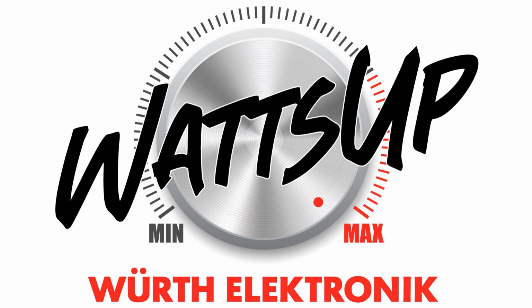So focusing on the graph shown on this slide, this core material could be used well for an inductor if the frequency of operation is between 1 and 3 megahertz tops. So after 3 megahertz, the mu double prime is very high and the material will have high losses, meaning that it can convert electromagnetic energy into heat. If we identify noise with a frequency higher than 3 megahertz, we could use this material to attenuate it.